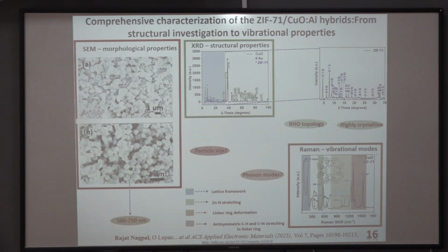Now to get insights about the structural features, here we can see the XRD pattern of the developed hybrids. Specifically the blue region corresponds to XRD peaks for ZIF-71, which are highly crystalline, and comparing it with other reported literature, it shows RHO topology. And to get insights about the phonon modes present, micro-Raman spectra classified in 4 different regimes,